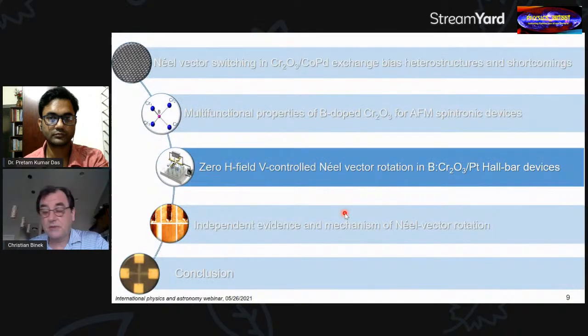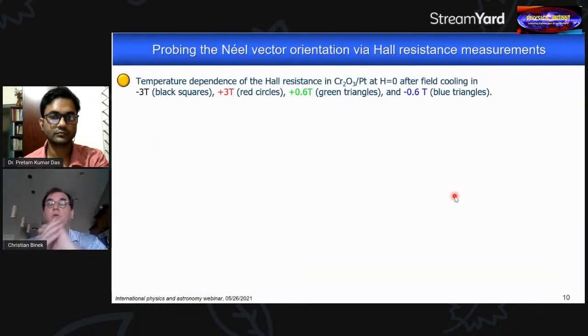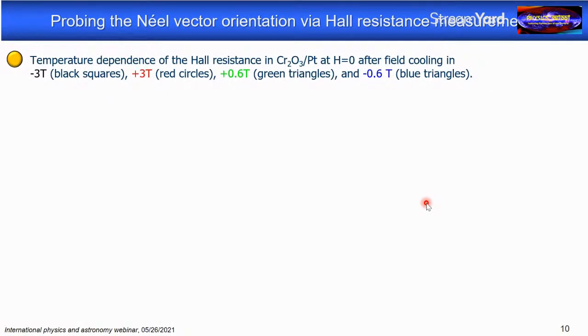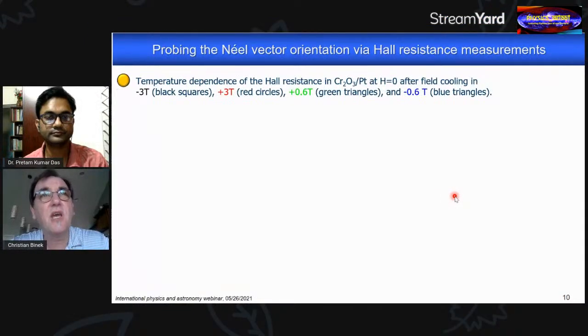Okay, now let me come quickly to the experimental data when we grow Hall bar device structures. So first of all, let me stress that what we now decided to do is, let's get rid of the ferromagnet on top. Let's not switch a ferromagnet at all. Why? Because we don't need it. We don't need it to read out in which state the antiferromagnet is. We can do that by Hall probing. By depositing a Hall cross on top of the antiferromagnet, we can actually read out the orientation of the boundary magnetization and use that to read out the state variable.